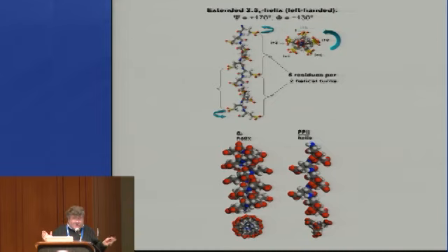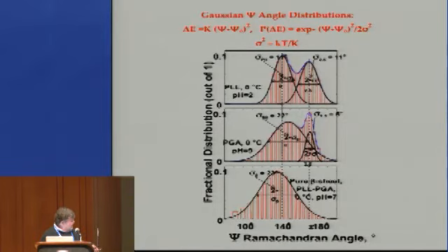Now that's a nice thing to know from the Raman spectra. You've got these 2 conformations in equilibrium. Actually, the amount of each tells you what the relative energy is. And if you take a look now at this conformational distribution in psi, you find out that it can be easily modeled in terms of 2 Gaussians, which is exactly what you would expect if you had a system defined by a torsional potential associated with the psi difference from the equilibrium state. And so you should have a Gaussian-like distribution, which is exactly what you see.